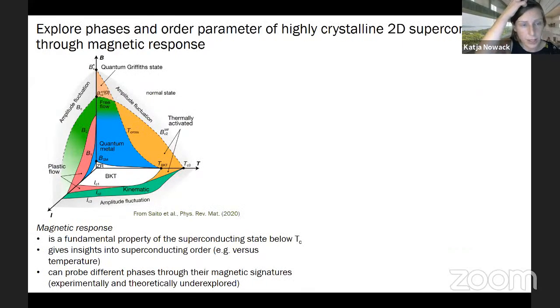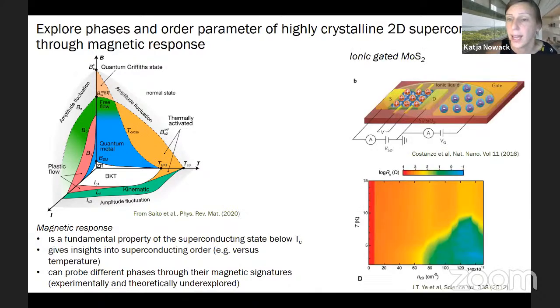But we would like to explore them through measuring their magnetic response. And the starting material that we got started on is actually ionic gated molybdenum disulfide, which superconducts. Molybdenum disulfide superconducts if you put enough charge carriers into it, and the number of charge carriers needed is on the order of 10^14 per centimeter squared. And so you need an ionic gate to actually get there.